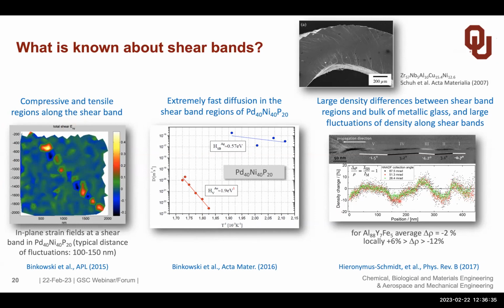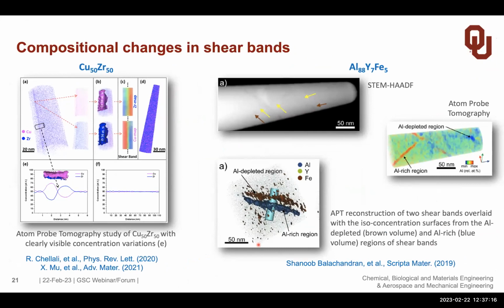We can also see, by analyzing the shear band in the microscope with another technique, density fluctuations. So we have regions where the density is higher, and regions where the density is lower. That all happens in a very short time of the shear band motion. And what people have also found is that the diffusivity, so the atomic jumps in the shear band, is accelerated by orders of magnitude. That's interesting because structural changes go hand in hand with the change of the property of the material.